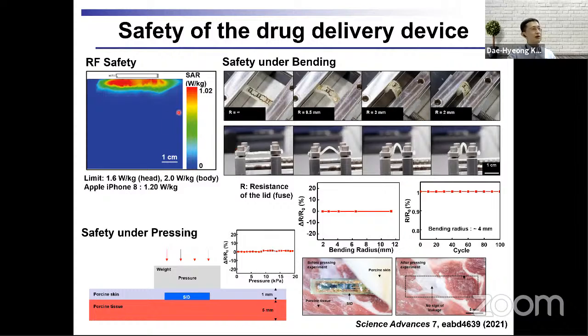And we tested the safety of the device systematically. First of all, we confirmed the SAR, specific absorption rate, which should be lower than federal regulation. And actually, our device SAR was lower than the Apple iPhone 8. And also, we tested mechanical safety, robustness of the device through severe, systematic bending and pressing experiments. And even after repetitive bending and pressing experiments, the device showed no mechanical fracture or malfunction.